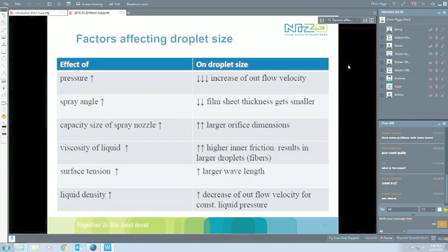If we look at how we can affect the droplet size, of course, the key ones are the pressure that we use, the atomization pressure: droplet size will very much decrease. We can start increasing our spraying angle, basically reducing the thickness of the sheets, and we can get smaller droplets. If we increase the capacity size of the nozzle, of course, particle size is going to increase. With viscosity of the liquids, we're going to get bigger particle sizes. We need to be careful there, of course. If we increase solids a lot, viscosity will increase, which is great for capacity, but we need to make sure that the particles don't get too big there.